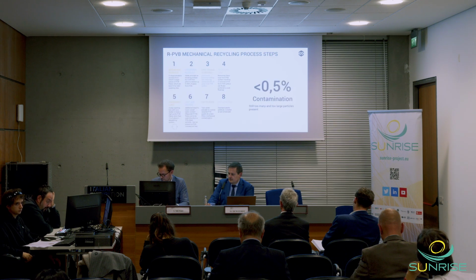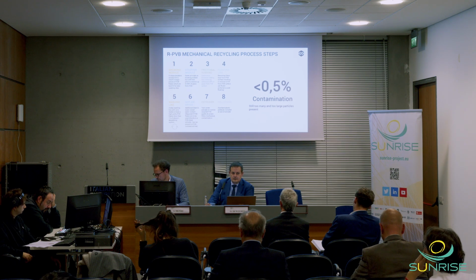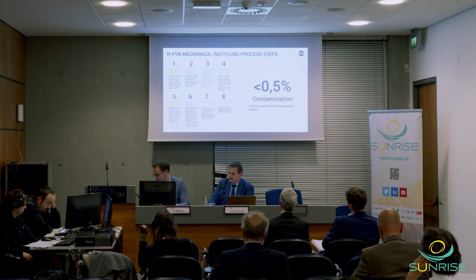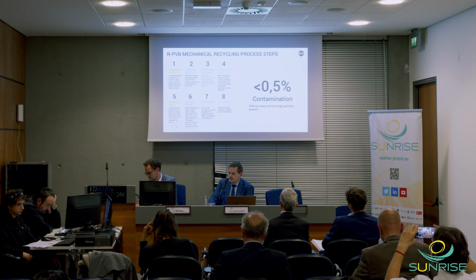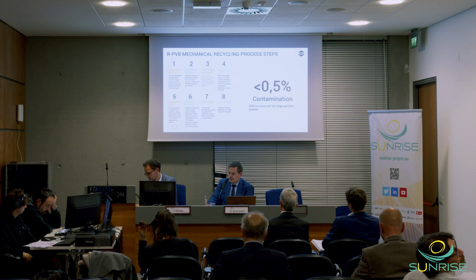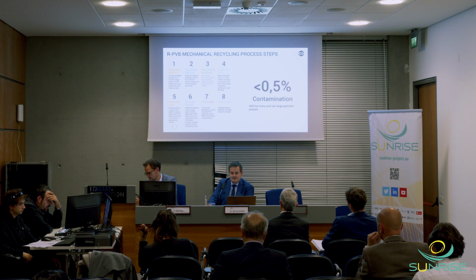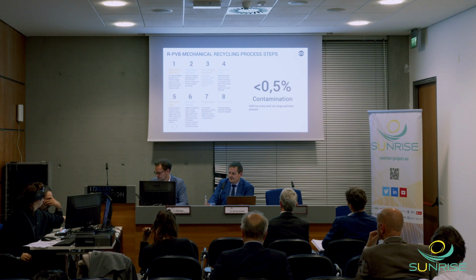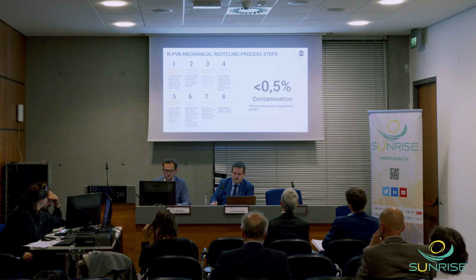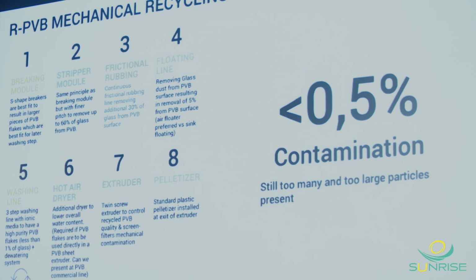For the last 2 years, I have been testing and investigating about 18 types of recycled PVB in a format. The slide on the left side, I will not go through in detail. These are typical phases that you see in a cleaning cycle or a recycling cycle. The best that I have seen in the market, which is about 6 months ago now, has a glass contamination level of less than 0.5%. That's the best that we are seeing.